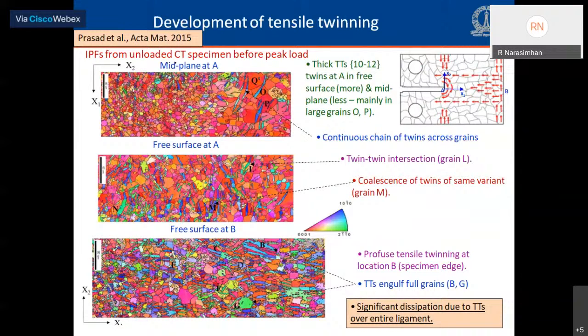Now, the left side set of images are inverse pole figure maps taken at two locations, at point A, which is very close to the notch root, and point B, which is at the far edge of the ligament. And at point A, Prasad took the scans both in the midplane as well as the free surface. They are shown on the top image and the one in the middle. The bottom one is taken at the free surface at location B.